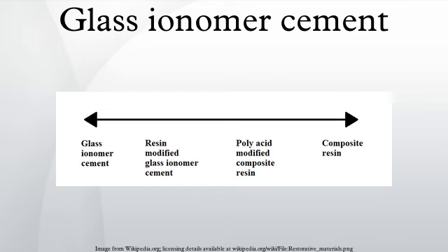The shear bond strength of conventional glass ionomer cements to conditioned enamel and dentin is relatively low, varying from 3 to 7 MPa. However, this bond strength is more a measure of the tensile strength of the cement itself, since fractures are usually cohesive within the cement, leaving the enriched residue attached to the tooth.